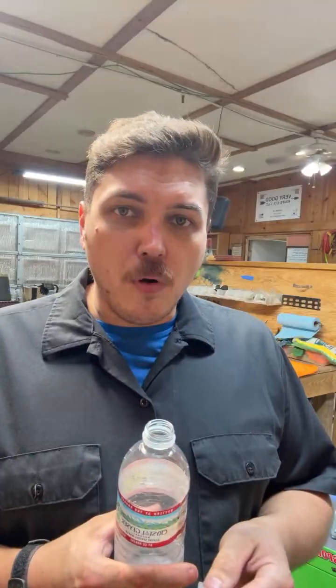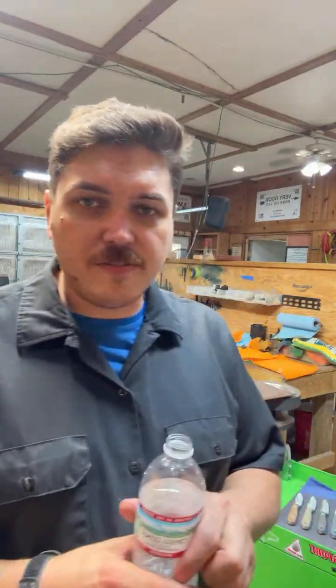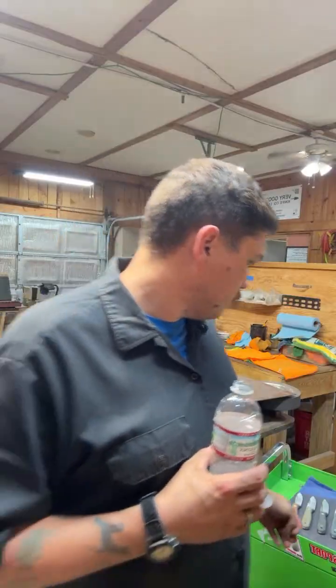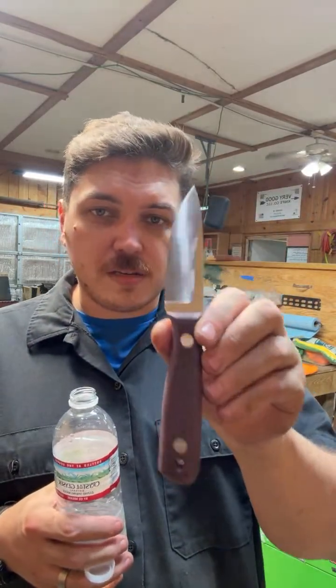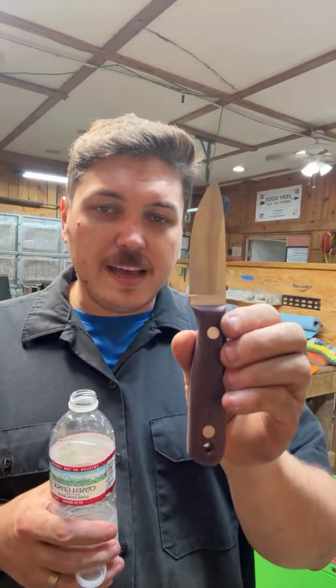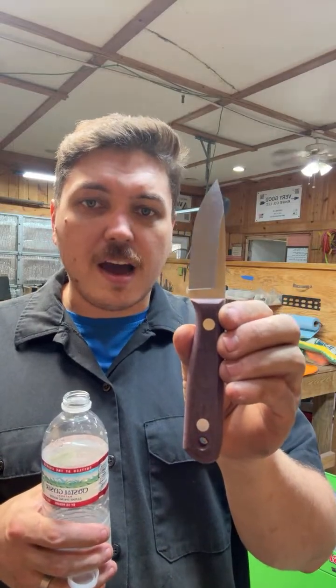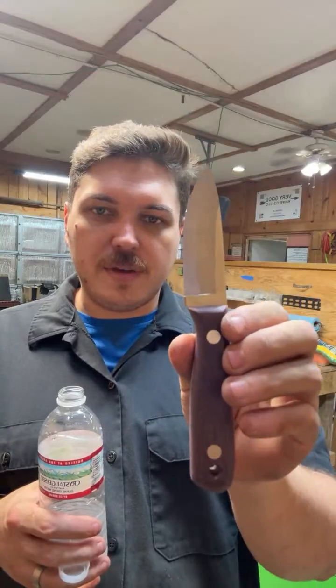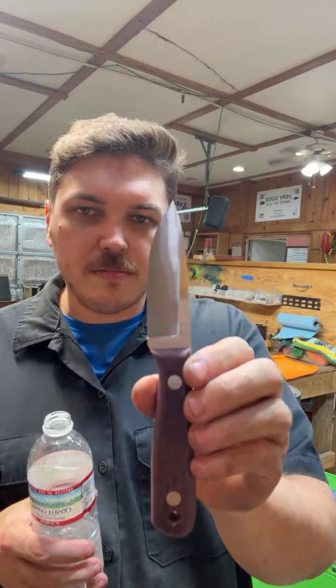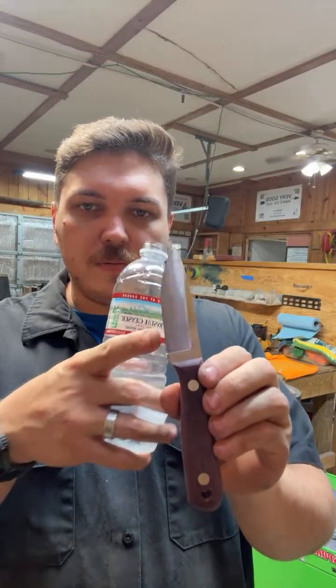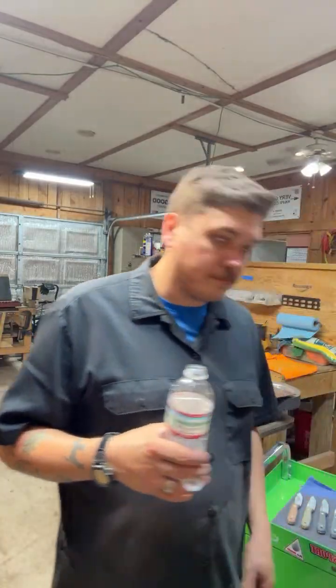I have to charge on average about $50 more for Nitro V than I do 80CrV2. The number one reason for that is because all my grinding, well, not all of it, but the majority of my grinding can be done with 80CrV2 before heat treat. These are oil quenched. I like a differential heat treat, it gives me better edge stability and a higher hardness at the edge, because I'm differential heat treating, meaning I'm not heat treating a flat bar of steel. The hardness is not going to be the same from the spine to the edge. It's not going to be the same. But that's just the way that stuff is made to be. It's okay to do that. But you can't really do that kind of thing with plate quenched or air quenched.